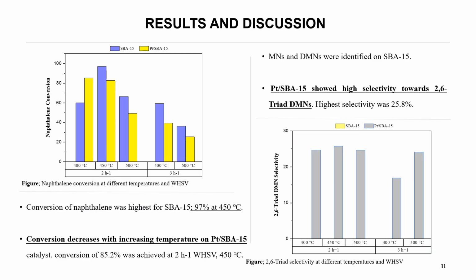To discuss the activity and effect of platinum loading on the catalyst, the naphthalene conversion, 2,6-dimethylnaphthalene selectivity, as well as methylnaphthalene yields were evaluated. From the conversions as shown in the graphs, the naphthalene conversion on SBA-15 is typically high. This could be linked to the large surface area and wide pore structure. Consequently, the highest conversion of 97% was recorded at 450 degrees Celsius. On the other hand, conversion decreased with increasing temperature on PT-SBA-15 due to the contraction of textural properties. However, a high conversion of 85.2% was still achieved.